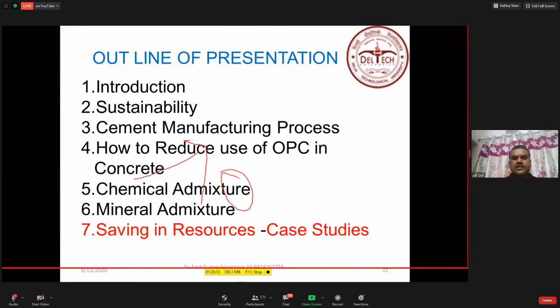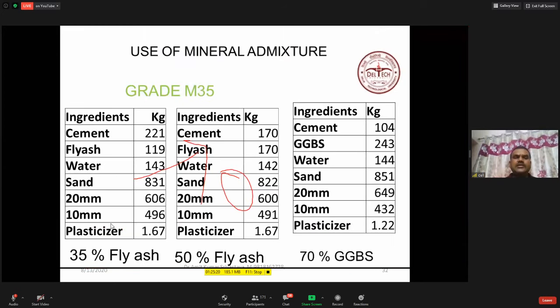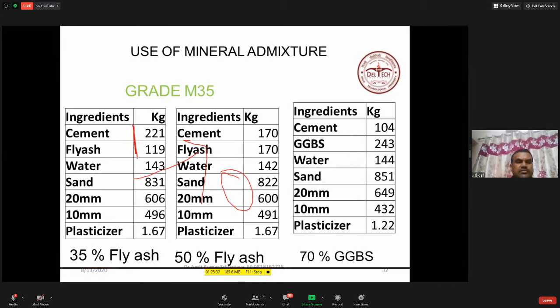So I have discussed mineral admixtures. Now I am talking about the last part of my topic, that is saving in resources and case studies. See now, our IS code says, you just remember that 340 kg cement I discussed. So our IS code says that you can use 35% fly ash if you are using normal concrete. If you are using self-compacting concrete, you can use fly ash up to 50%. You see, so OPC 221, 119. If I am using 35% fly ash, and if I am using 50% fly ash, then it is 170, 170.